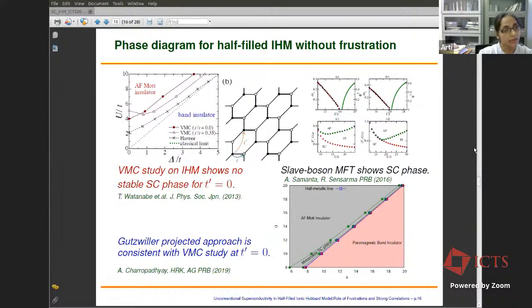Now, in the absence of next neighbor hopping, the half-filled Ionic Hubbard model has been studied by other approaches also. So let me show you the comparison of the phase diagram that we obtained from DMFT plus CTQMC and the Gutzwiller projected renormalized mean field theory with these other calculations. Watanabe and others studied the half-filled Ionic Hubbard model using variational Monte Carlo, and they do see a direct transition from a band insulator to an antiferromagnetic Mott insulator.